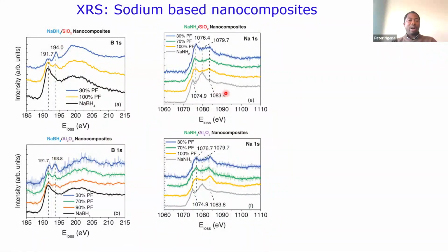And a very remarkable one is that here we look at the sodium amide-based composite, because for the other one we had something like a BO-like bond, since there is boron there. So my expectation was that if we also have something like an NO bond for the sodium amide-based sample, then that will be conclusive that we really have interaction between the surface groups of these materials and our electrolyte, the active electrolyte material.